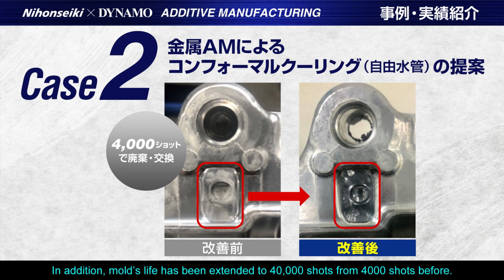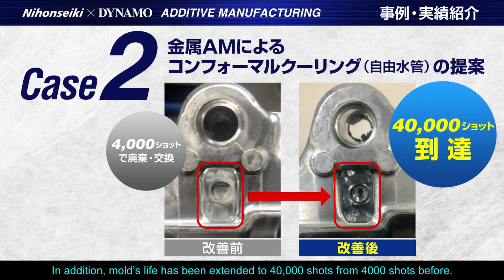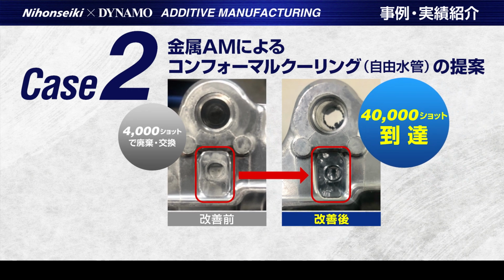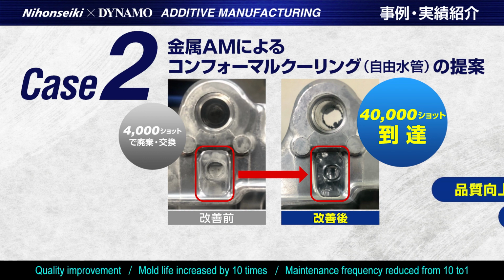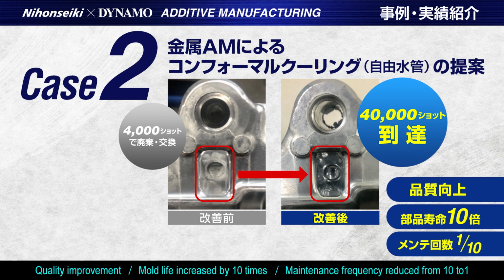As you can see from the photo, it is totally different when comparing these two inserts. In addition, the mold's life has been extended to 40,000 shots from 4,000 shots before. As a result, the frequency of die maintenance was reduced from 10 to 1.